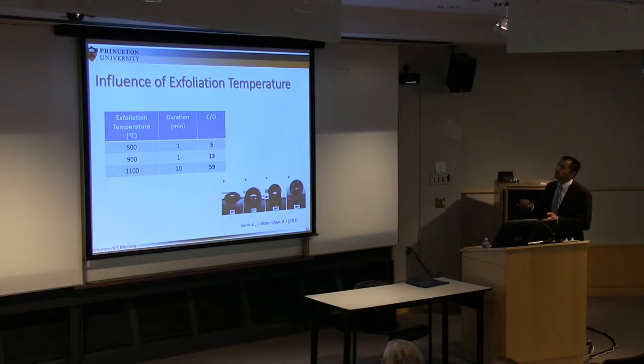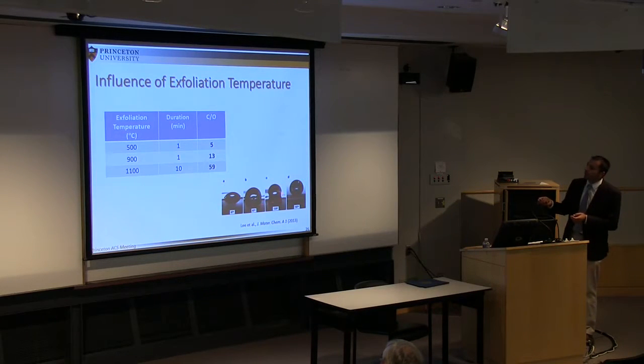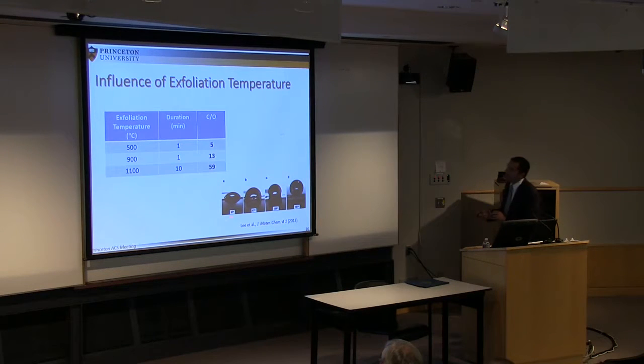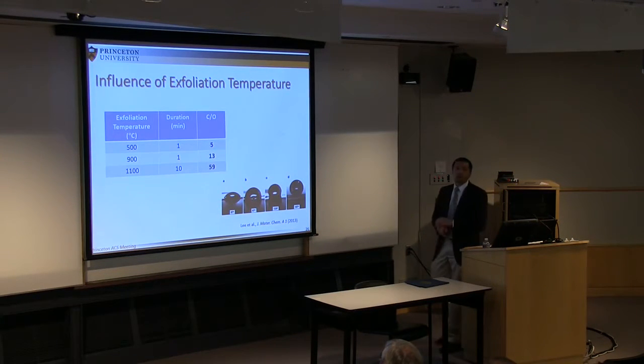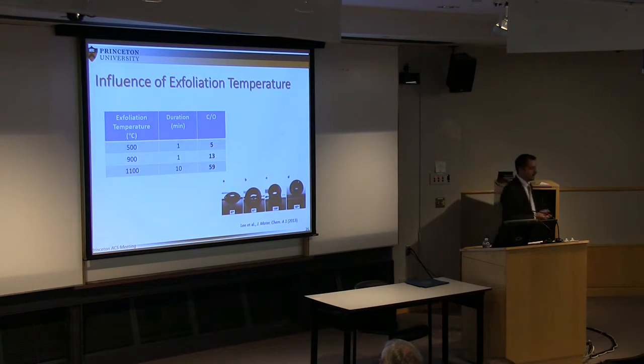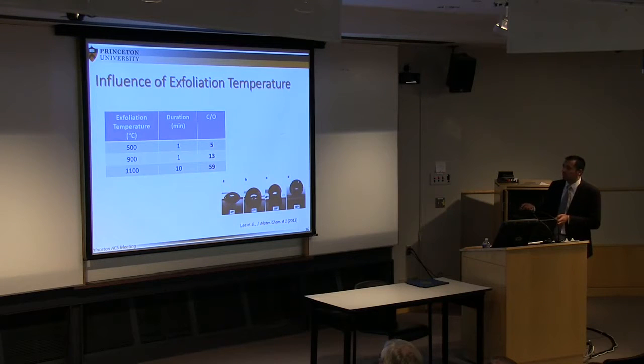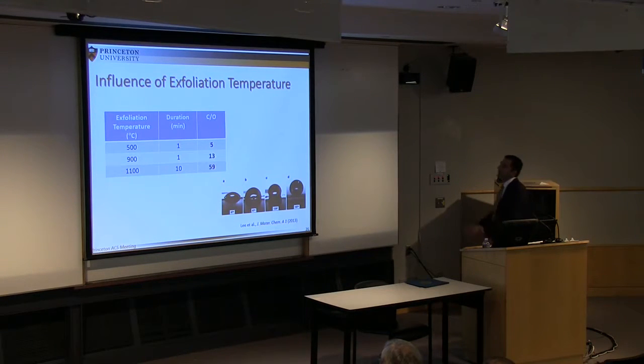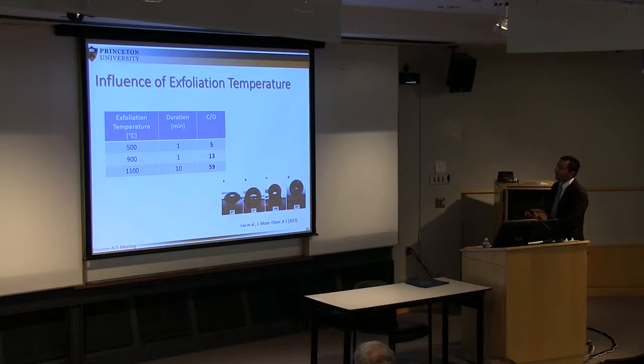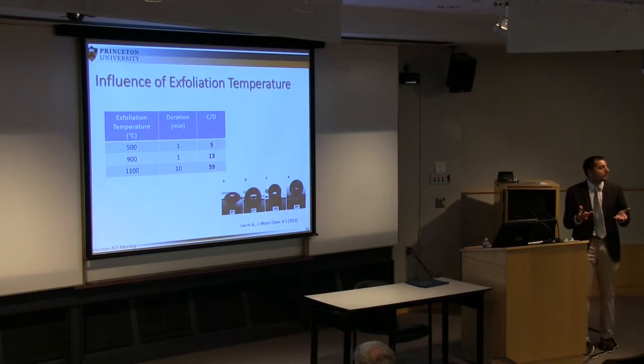So along this heat treatment, because you are changing the chemical structure, this can be evidenced also if you do contact angle measurement. So on the left here, you have the graphene with a low C/O ratio, so 5 or less. It's hydrophilic, so it wets the surface quite well. I mean, water wets the surface of graphene quite well. But as you are reducing your material, you see now the angle is going up, 87. It becomes hydrophobic. Why? Because you don't have those groups anymore that like water.